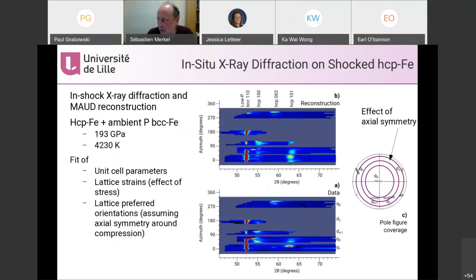This is the type of X-ray diffraction data we managed to collect and reconstruct at the MEC beamline. So this is an example. It's HCP iron at 193 GPa and 4,000 Kelvin, based on the unit cell volume. The bottom is the data, and on top is the reconstruction. And you can see diffractions from the ambient pressure BCC, which has not been reached by the shock yet, and then of the high pressure HCP phase.